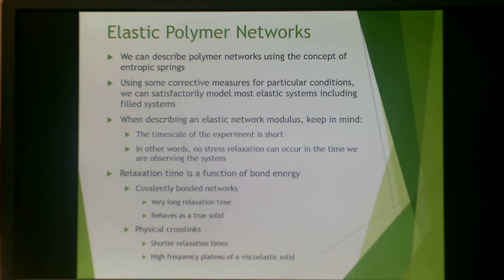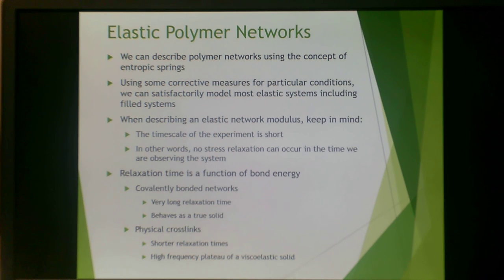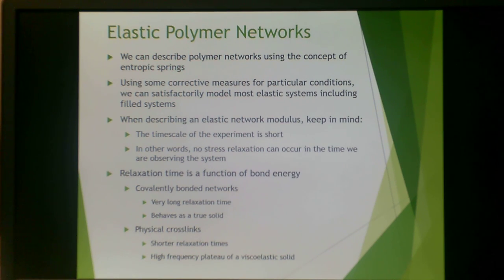To summarize these three parts on elasticity and high Deborah number measurements: we can describe polymer networks using the concept of entropic springs, with corrective measures for particular conditions that allow us to satisfactorily model most elastic systems, including filled systems. When describing an elastic network modulus, the timescale of the experiment must be short compared to the timescale for stress relaxation — meaning no stress relaxation occurs during observation, giving solid-type, high Deborah number behavior. Relaxation time is a function of bond energy; covalently bonded networks have very long relaxation times and behave as true solids, while physical crosslinks have shorter relaxation times but show a high-frequency plateau of a viscoelastic solid. This concludes Elasticity, or High Deborah Number Measurements, Part 3, Video 2.